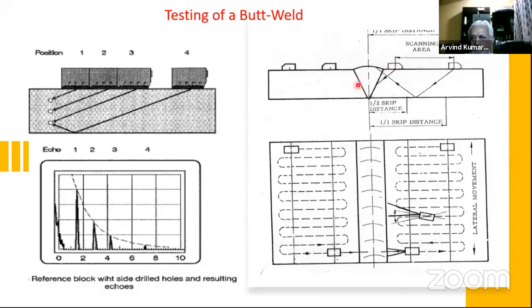Again, I have taken this picture to explain in parallel. Once having got the DAC, depending upon the thickness, I will set the range using a V2 block. In this case, suppose this is 20 mm. If I set a range of 125 mm, it will give me a good range to cover my top surface and the bottom surface. I will set the range of 125 mm using that V2 block. Once that is set, I only have to scan. If I put the probe here, I get the indication from the root. If I put the probe here, I get the indication after a bounce, when I reach the surface. So if I scan between these, I'm scanning the root as well as the top surface. That means I'm scanning the entire volume of the weld.